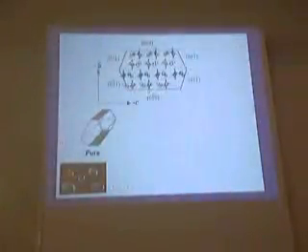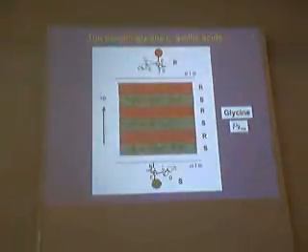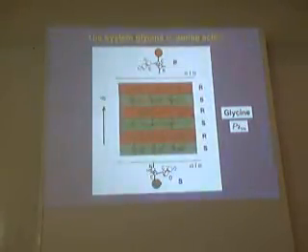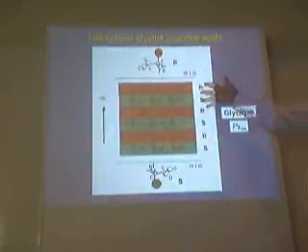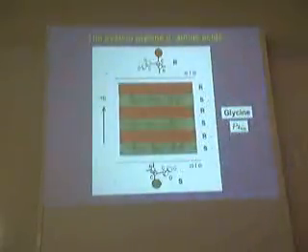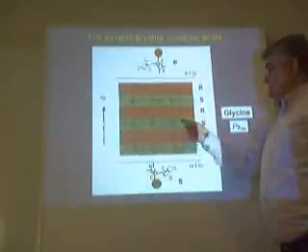Okay, I go back. So let us now look at the crystal. Glycine has three different polymorphs, alpha, beta, gamma. If you crystallize glycine in water, you are getting the centrosymmetrical crystal. The beta and gamma polymorphs are enantiomorphous, but they don't grow in water. If you grow them in water, you are generating this alpha form of glycine. This is a centrosymmetrical crystal. As you can see, these crystals have centers of symmetry.